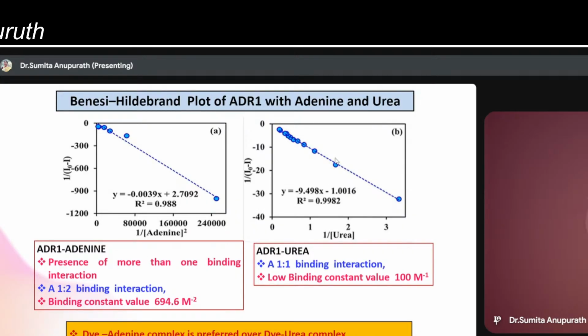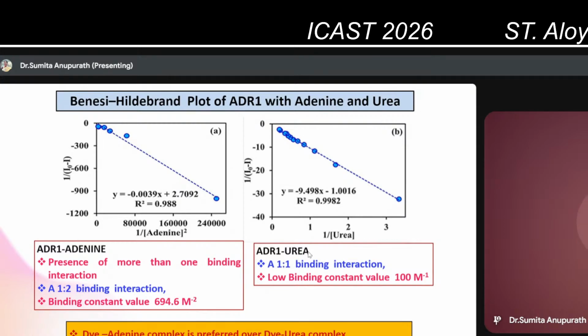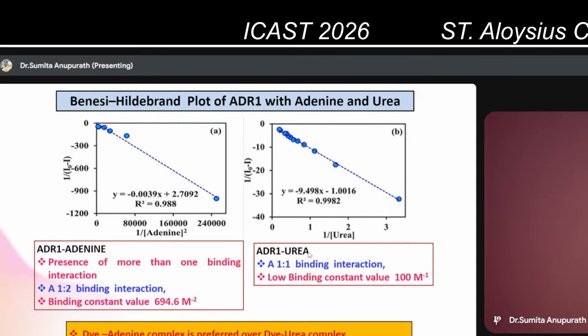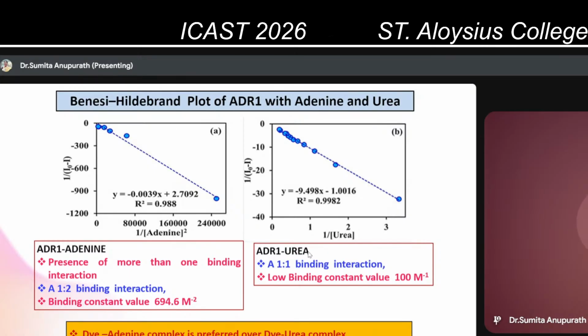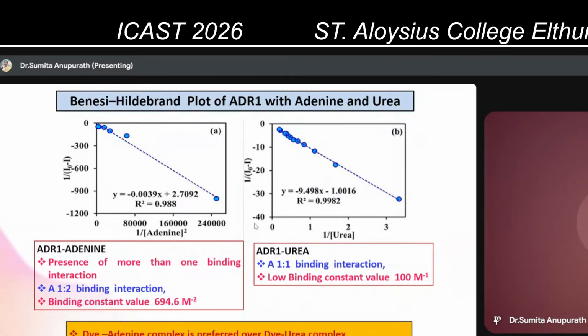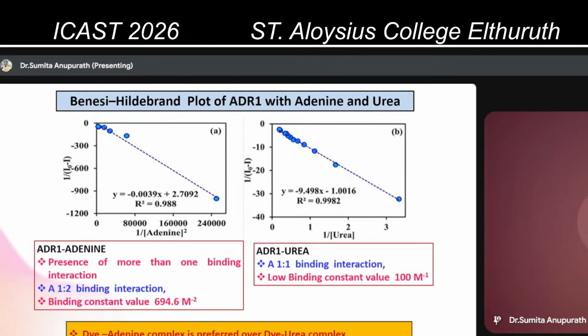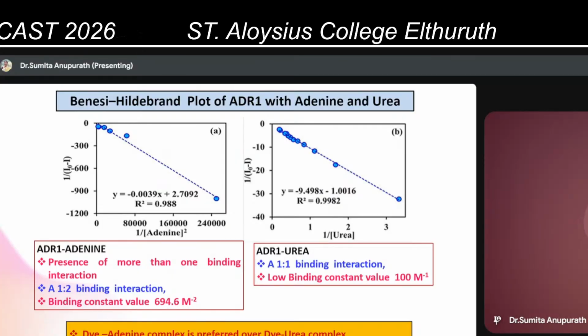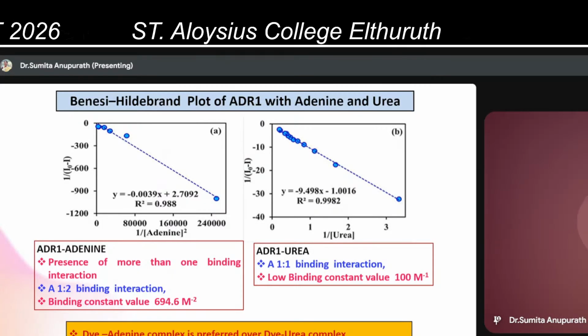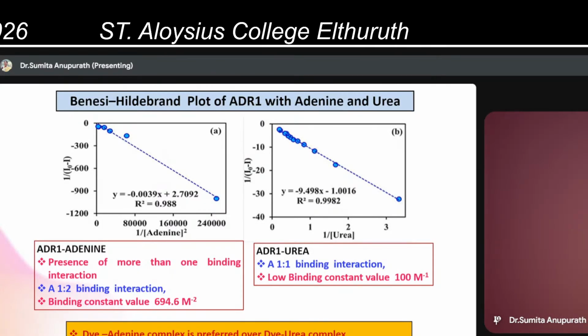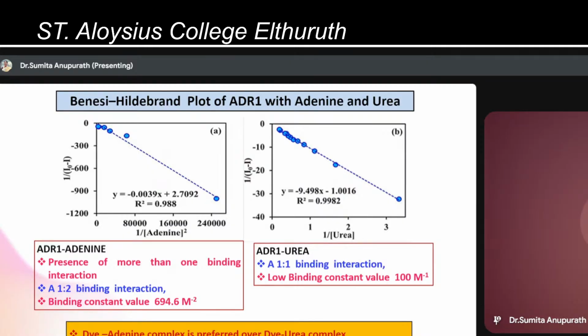with urea, our dye was able to form only a 1:1 complex, that is, one dye molecule binding with one molecule of urea. The binding constant was also found to be very low. So from this we can understand that the dye prefers to bind with adenine and form a more stable complex than forming a complex with urea.